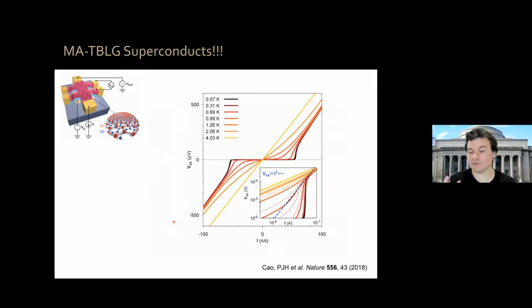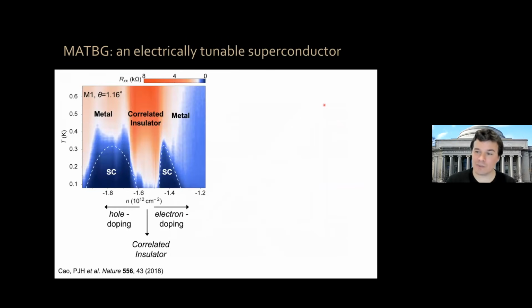You can in fact do any test of 2-dimensional superconductivity that you want, okay? For example, you can run a finite current, and you see 0 voltage dissipated until the moment the system switches to a resistive state. You can apply a magnetic field, I'm not showing it here. You can also do Josephson phase coherence experiments. This thing is a 2-dimensional superconductor. And not only that, the system is an electrically tunable superconductor, because remember, we have this field effect transistor geometry. So that means that if we start from these 2 holes per Moiré unit cell, where we have this correlated insulator state, okay? Now we can add a few more holes to the system, and the system has this superconducting dome. If we add a few electrons instead, we go in the other direction and we have another superconducting dome. And we can do this electrically.